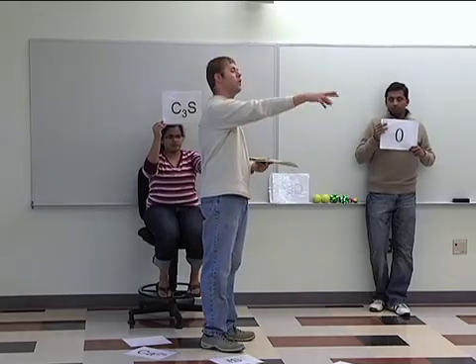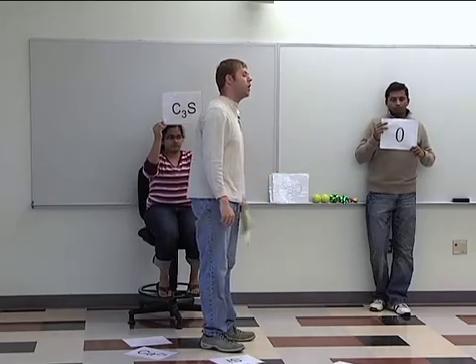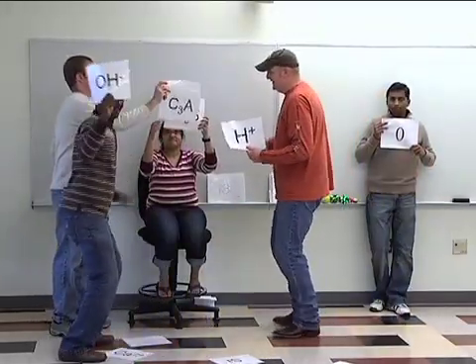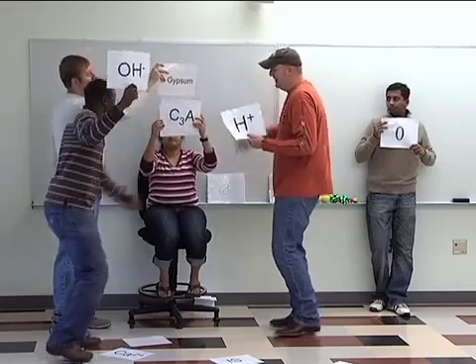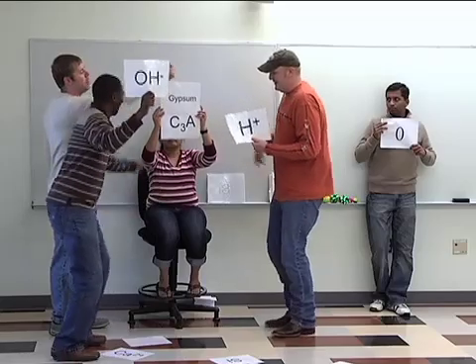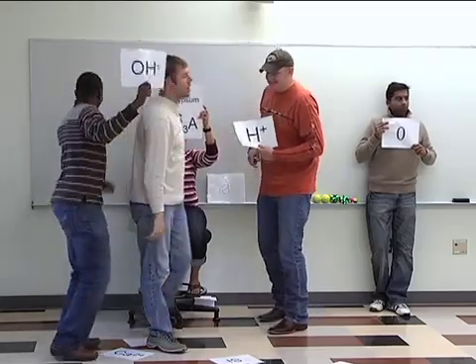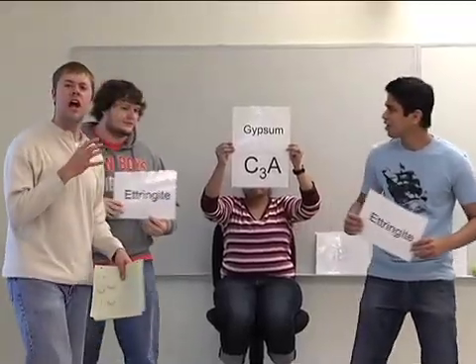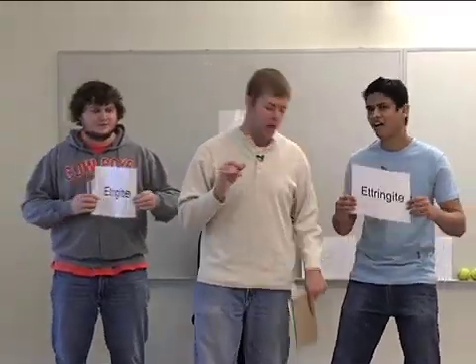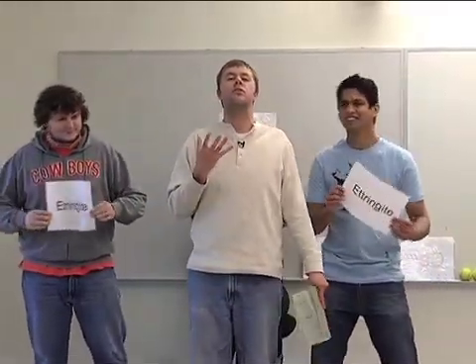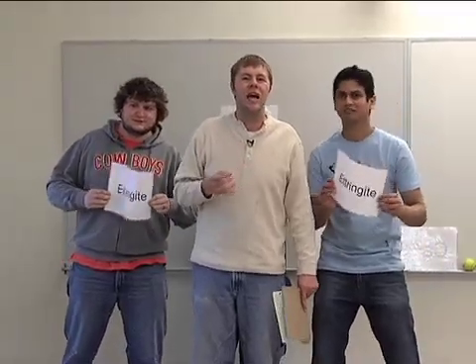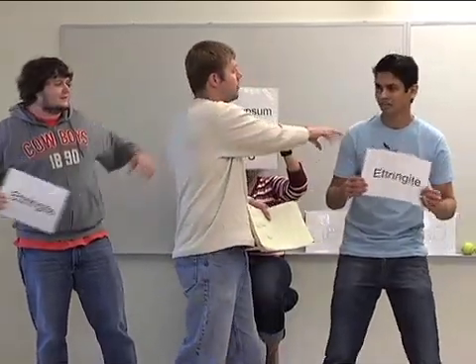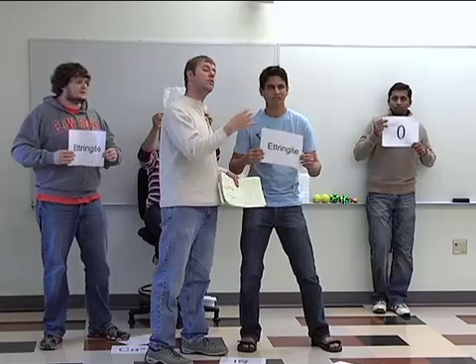Also at this early stage, we change from C3S to look at C3A. The C3A, the gypsum, and the water combine to form ettringite. Our ettringite is formed — it's actually born. The water molecules are consumed in this process. This ettringite is not the ettringite we usually think about — not the needle-like crystals. This is ettringite in solution; we don't really know exactly what it is, but it's in solution, kind of swimming and flowing around. It will flow off to the side as it remains here from now until some point in the future.